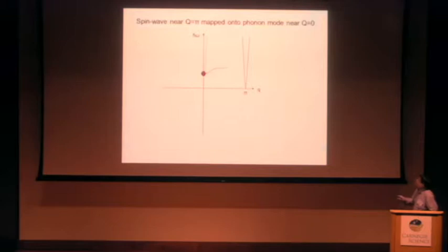Strong enhancement of intensity when the system enters the antiferromagnetic phase. But the intensity enhancement occurs where the lattice mode is dominant. Here, there's no spin wave intensity. But from the temperature dependence of the observation, it is reasonable to propose that this enhancement is actually related to what's happening in the magnetic channel.